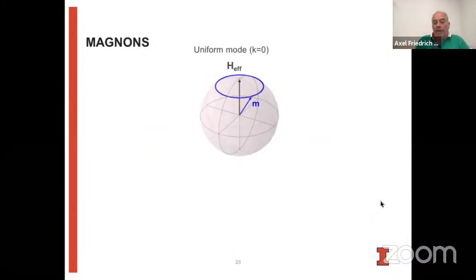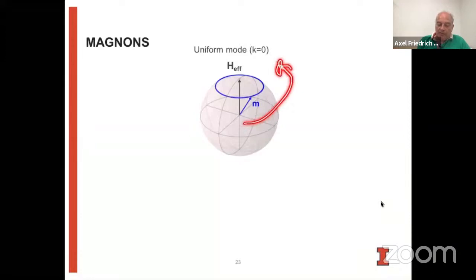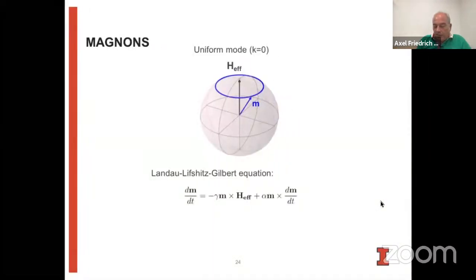Okay, so now let's go back and think about magnons. Most of you are familiar, but I'll briefly go through the basic motions. If you put a magnetization into an effective field and the magnetization is not aligned with this effective field, the magnetization will precess around this magnetic field. And if the whole magnetization in your material does all the same thing, that's what we call the uniform mode. And we can describe this by the Landau-Lifshitz-Gilbert equation, which has two components, one that describes the magnetization precession around the effective field. And then there's another component which describes magnetic damping. And so this magnetic damping will over time align the magnetization with the direction of this magnetic field.